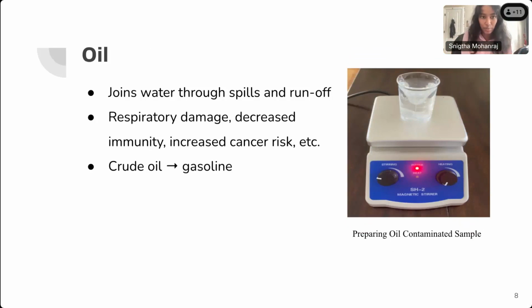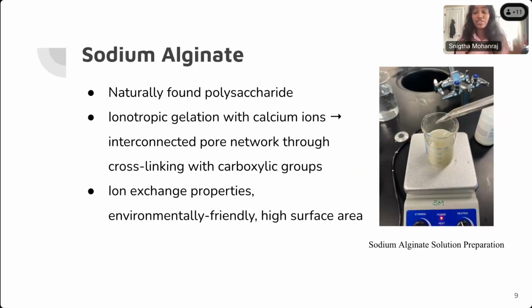So the first compound that I'm using in my solution is sodium alginate, which is a naturally found polysaccharide. It's most noted for its ionotropic gelation with calcium ions, in which it basically forms an interconnected pore network through cross-linking between the ions and the carboxylate groups of the sodium alginate. And this gives ion exchange properties. It's also a very environmentally friendly material, and it has a very high surface area, which means that it's very applicable when using it for water contaminant removal.